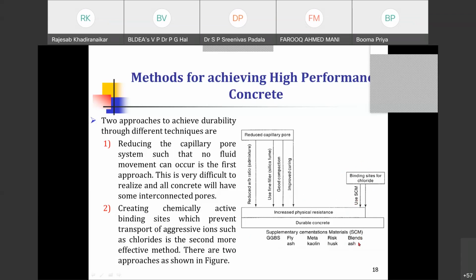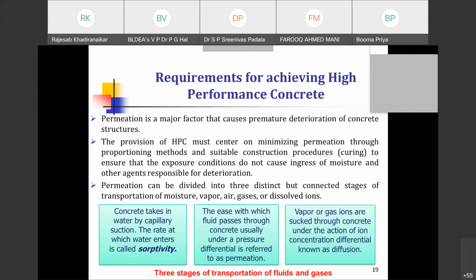It may be a blend of fly ash or other materials, rice husk ash, metakaolin, fly ash, GGBS, or you can use these individually, or you can go for binary or ternary combinations of these. Then you will be providing additional binding sites wherein additional silica gel will be formed, and your concrete becomes more dense, and then you will be able to achieve the high performance concrete. And of course, as you already know, the ideal high performance concrete will have high performance, will have economy, will have resistance to wear and deterioration, and will also have resistance to weathering. These things are achieved by these two techniques. When you make these changes to the mixes, then you will achieve these things.